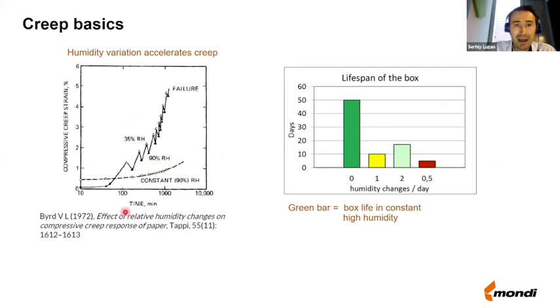On this graph, you see how much the paper is deforming under constant load. On the X axis, you have time. On the Y axis, you have deformation. So you see that if you keep the same load over time, paper will deform more and more until at some point it will just collapse. But interestingly, you can see here that if you use a change in relative humidity, in this case from 35 to 90%, then the failure happens much faster. Here you have a logarithmic scale, so this difference is actually much bigger than it looks visually. So the paper, and the same applies to boxes, collapses faster at changing relative humidity than at a constant relative humidity condition.